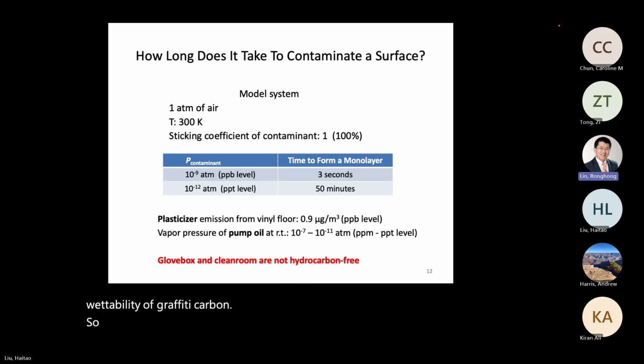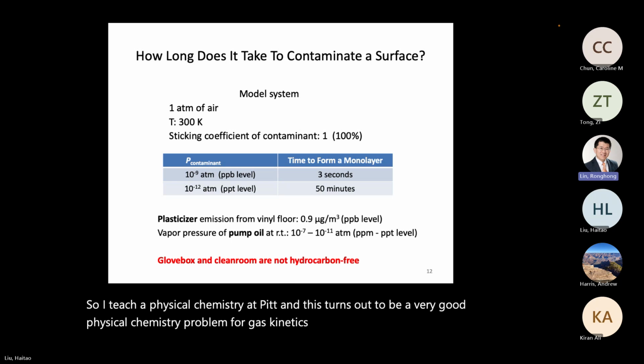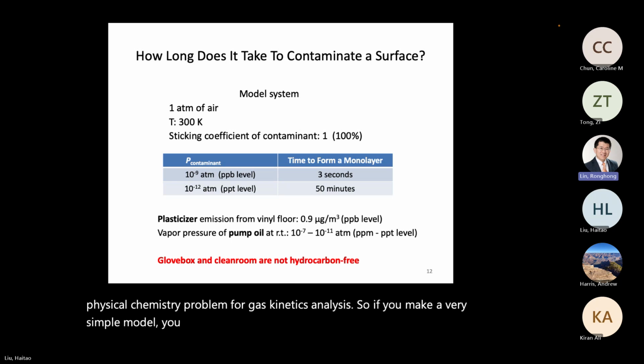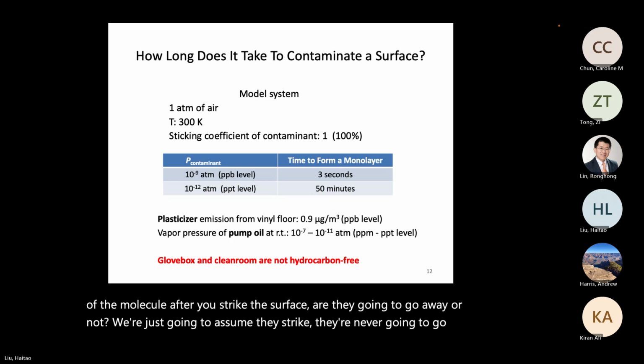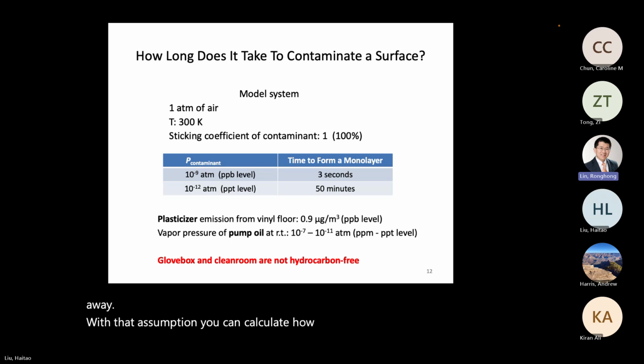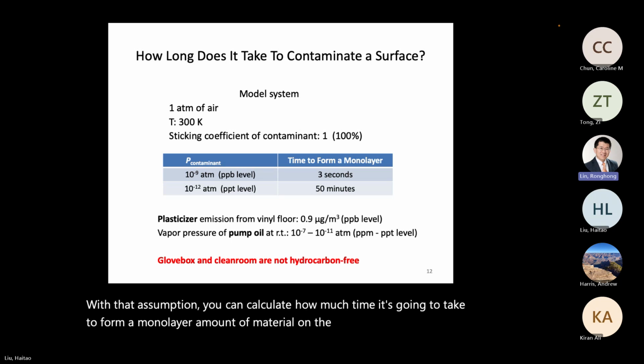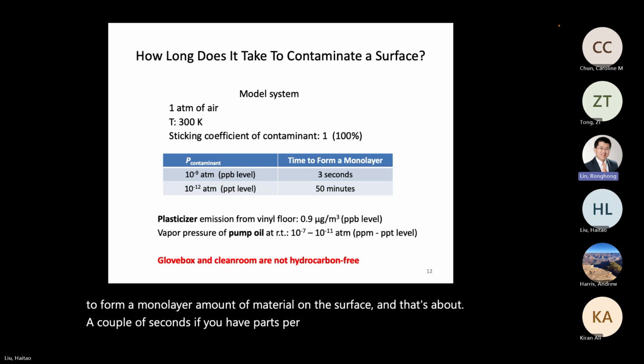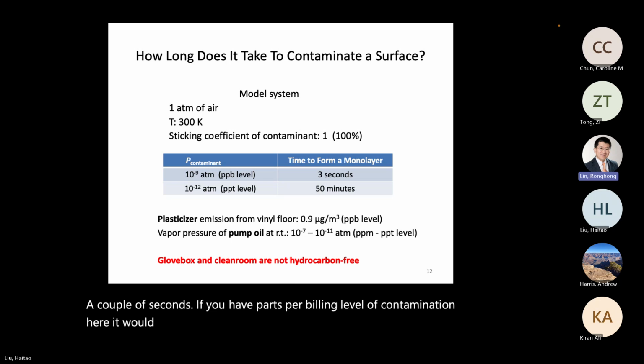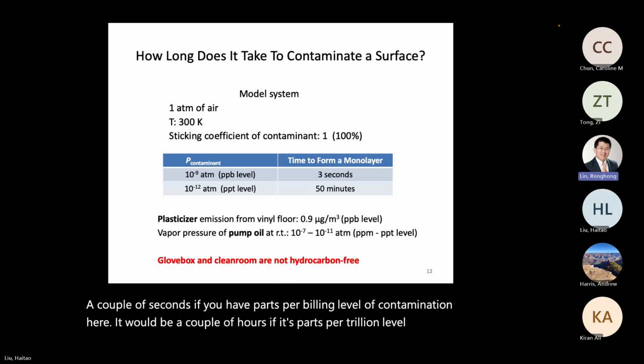So I teach physical chemistry at Pitt, and this turns out to be a very good physical chemistry problem for gas kinetics analysis. If you make a very simple model, 1 atmosphere pressure, room temperature, assuming the sticking coefficient, which is the likelihood of the molecule, after it strikes the surface, going away or not, we're just going to assume if they strike, they're never going to go away. With that assumption, you can calculate how much time it's going to take to form a monolayer amount of material on the surface. That's about a couple of seconds if you have parts per billion level of contamination in air. It would be a couple of hours if it's parts per trillion level of contamination in the air.